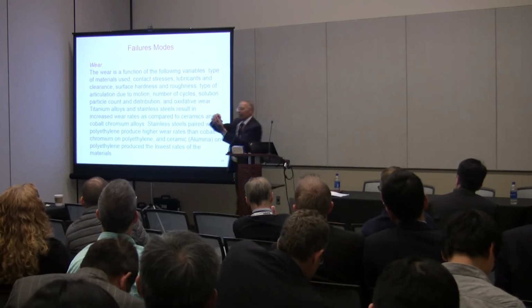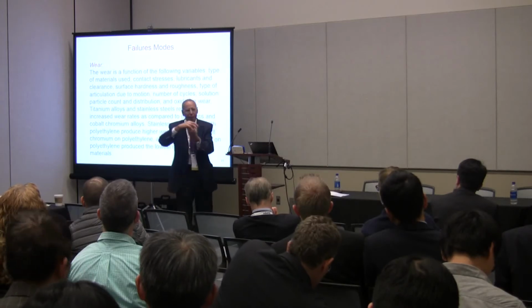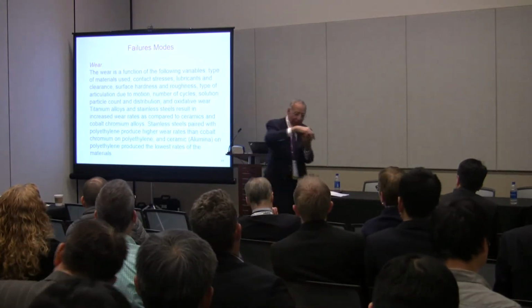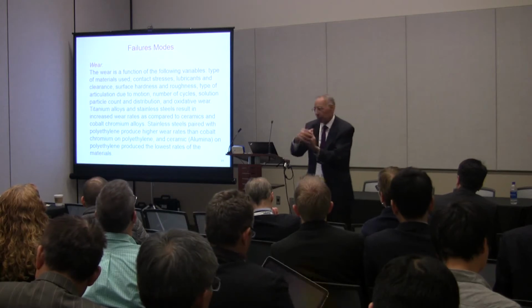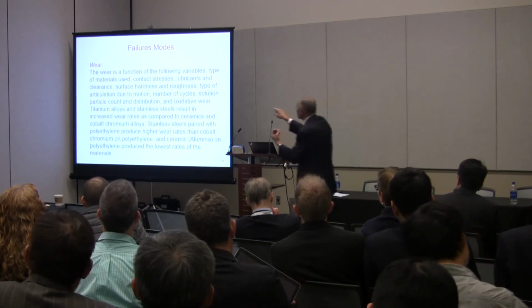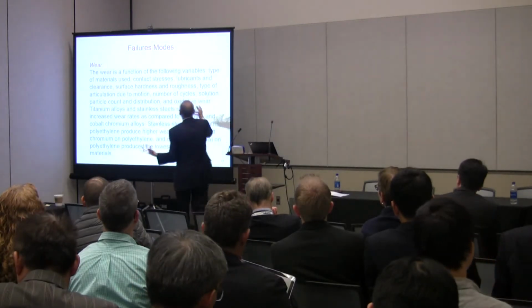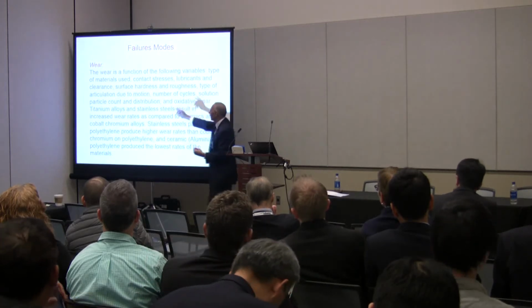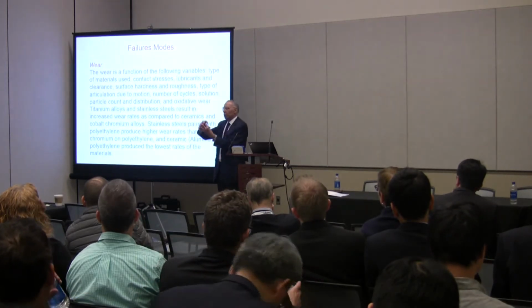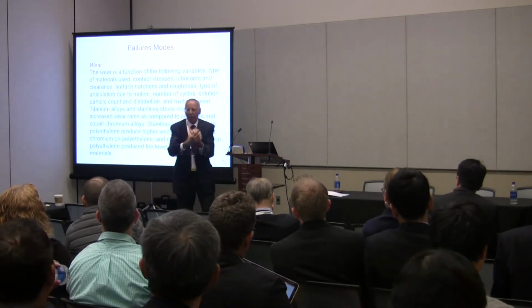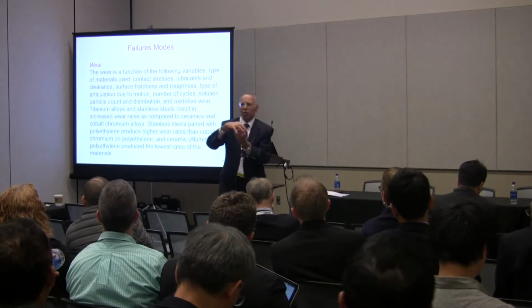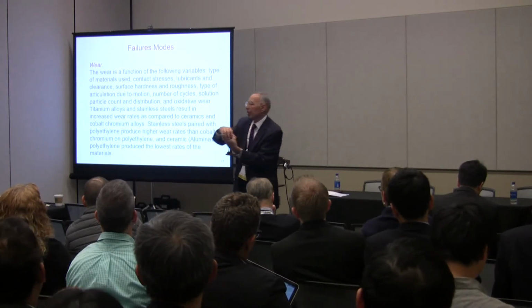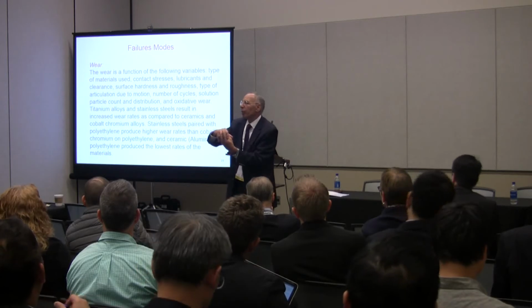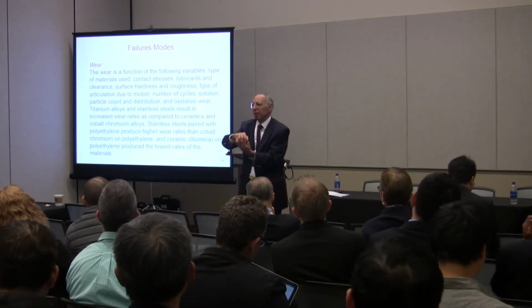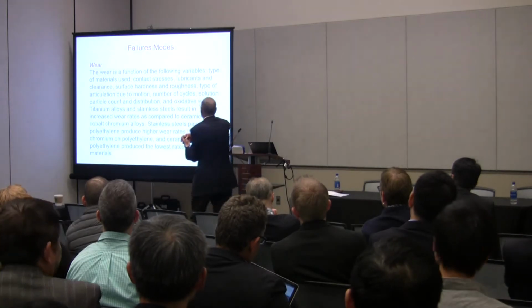If you have a socket and a ball rotating, depending on your motion and your weight, the amount of debris is a function of the material you have and the motion exerted on it. The amount of wear depends on the material used, the contact stresses, the lubricants, the clearance, and the surface hardness and roughness. When you have a surface like a ball, it is not exactly a ball, and you put it in a socket, the wear is non-uniform. Some areas will wear sooner than others, and the load distribution changes continuously. Wear changes with time.